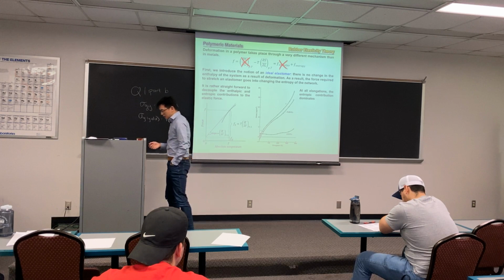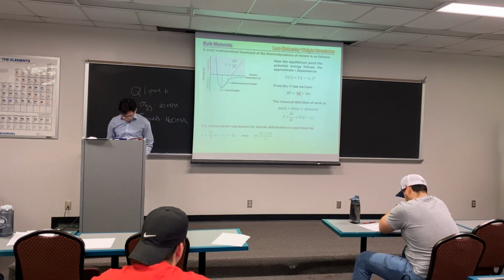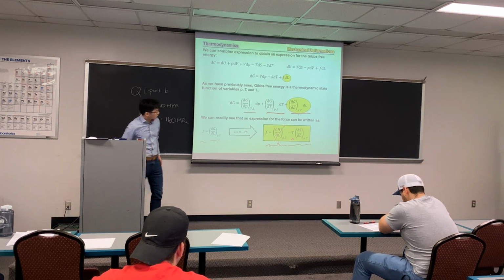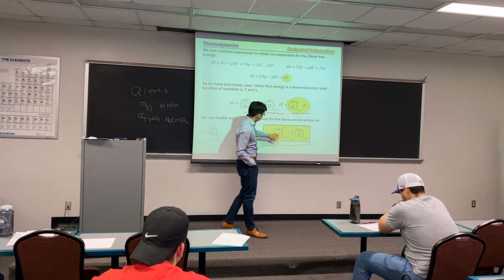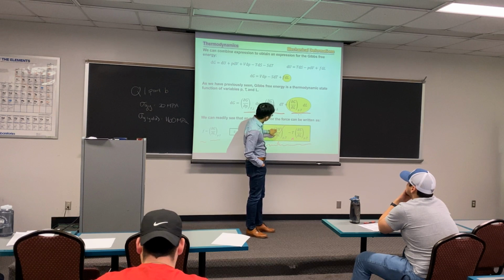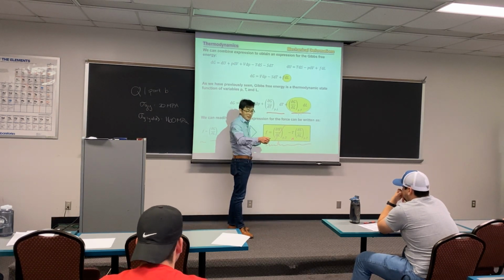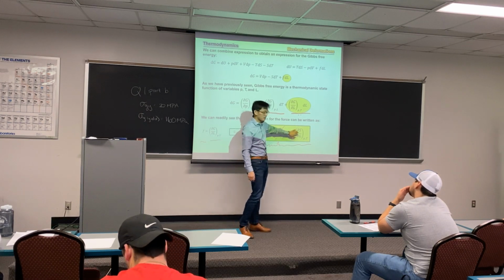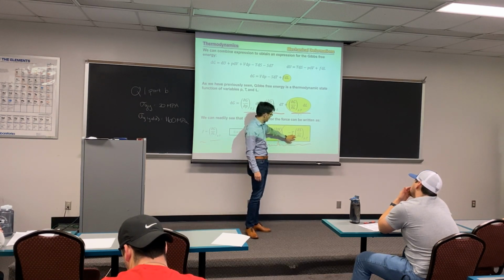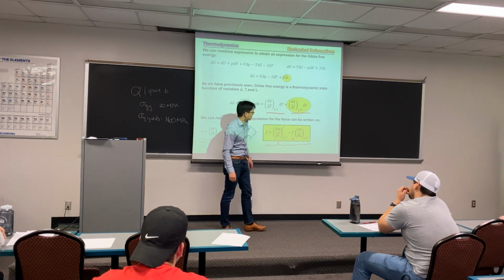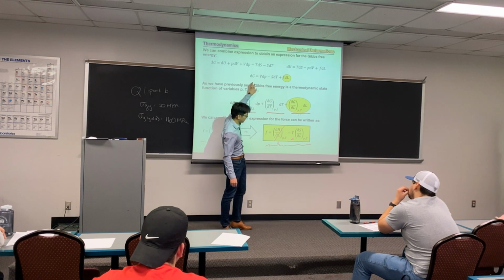At the end of class, we concluded that your force can be linked to the partial derivative of energy with respect to length or displacement, as well as the partial derivative of entropy with respect to displacement. All these are at constant pressure and temperature, so we don't need to worry about the rest of the terms that show up.